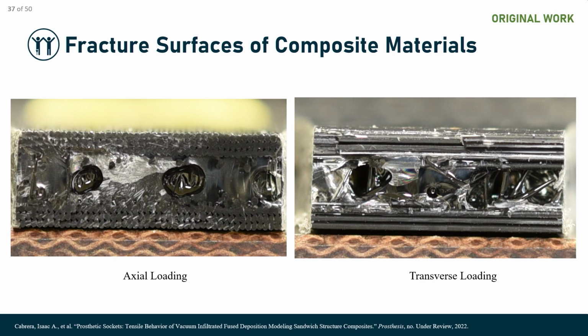By a huge amount, these are like 1 millimeter, so it's very hard to see with your naked eye, but they're very real, and they dramatically decrease the strength specifically. If you see those lines, I'll mouse over right here, these lines right here, these are hackles, indicating where the failure point initiated from. In these materials, we can really see that our failure is primarily caused by this porosity. Although we tried to minimize some of that porosity in our infiltration and manufacturing process, it still existed, and it still dramatically decreased our strength specifically. Any future research would have to address that.